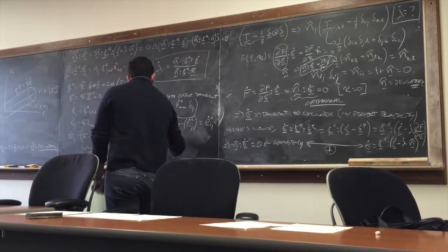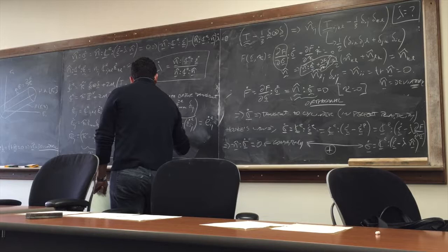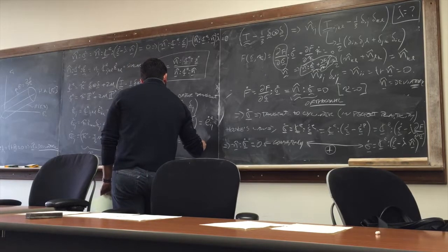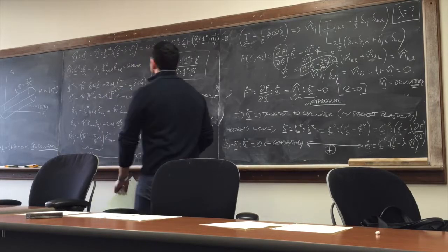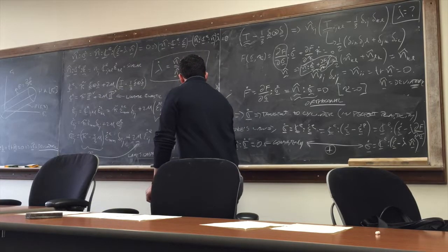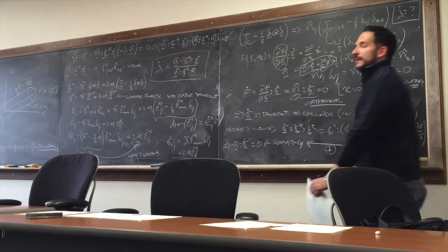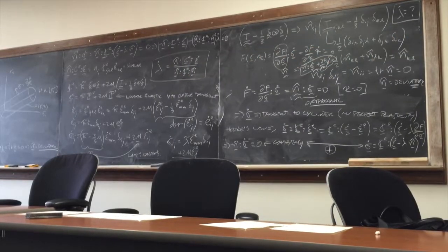So you typically say sigma dot ij equals lambda wiggle times the volumetric part of the strain rate, plus 2 mu times the full strain rate. Okay? I just wanted to go through this in additional notation so you feel comfortable with the notation we're adopting.